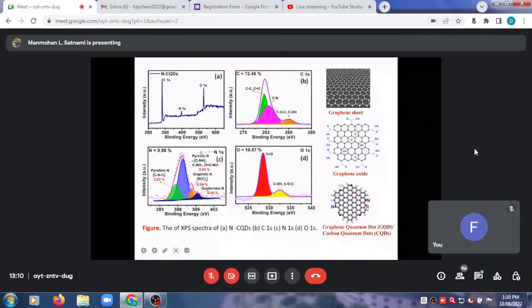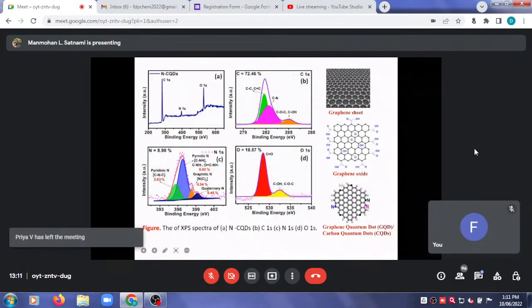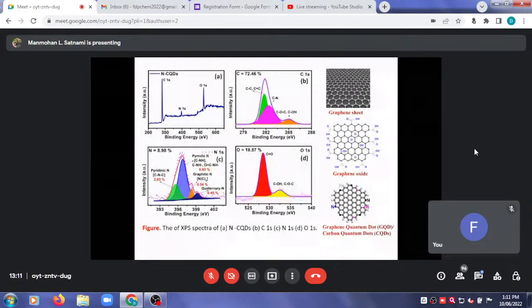A very interesting thing happened with nitrogen. You see, nitrogen can be doped in the carbon quantum dot in different forms: in the form of pyridinic, in the form of pyrrolic, or it could be graphitic, or in the form of amidic, or quaternized nitrogen. So this XPS spectra actually tells us how different kinds of nitrogen doping are present in the carbon quantum dot. And if you remember, I showed you. Let me go back to the slide.